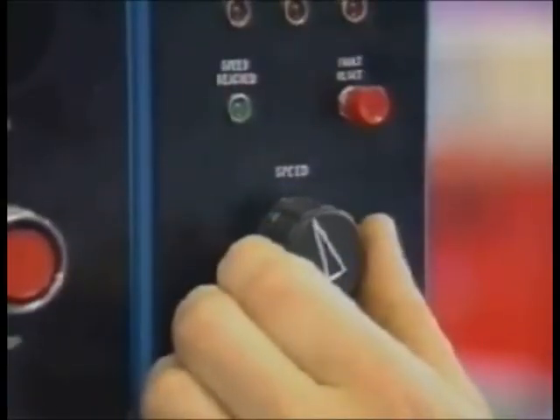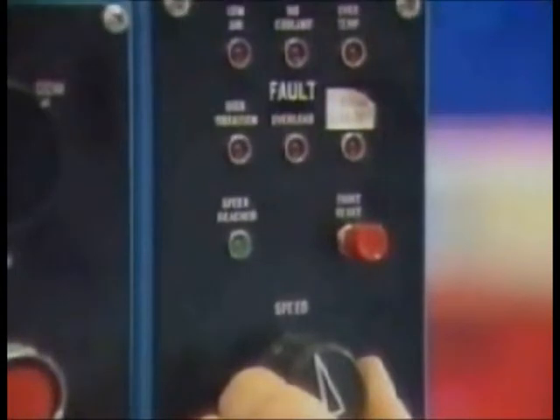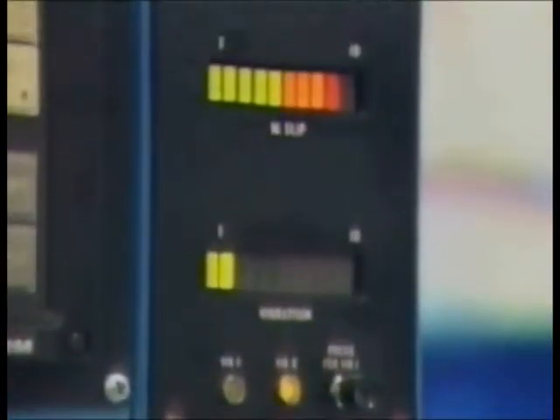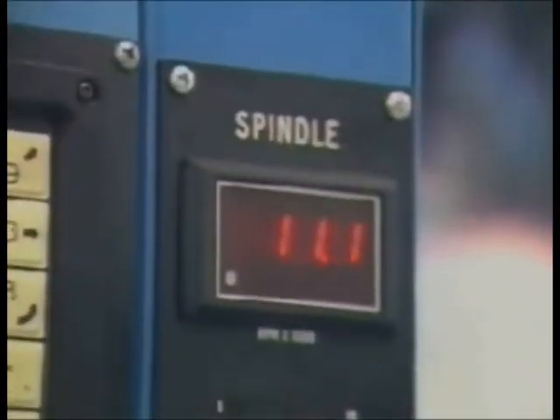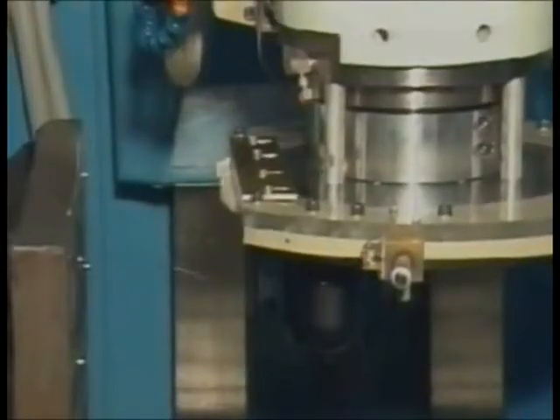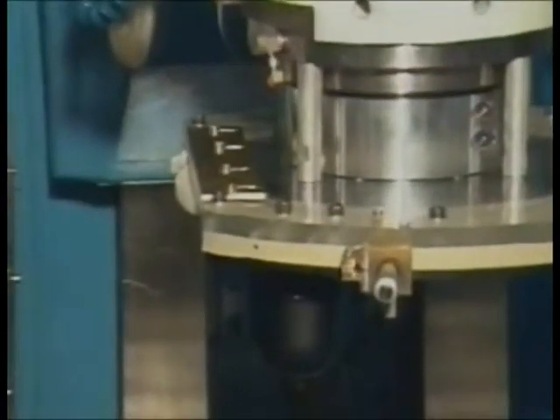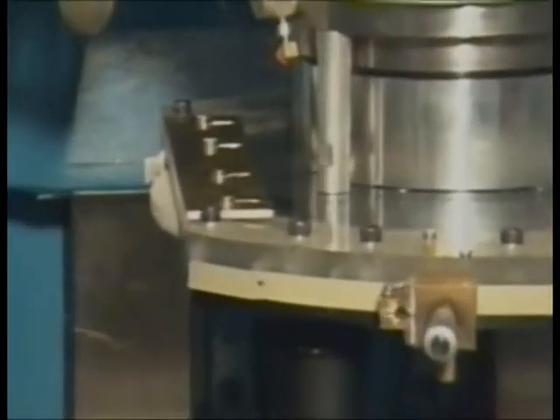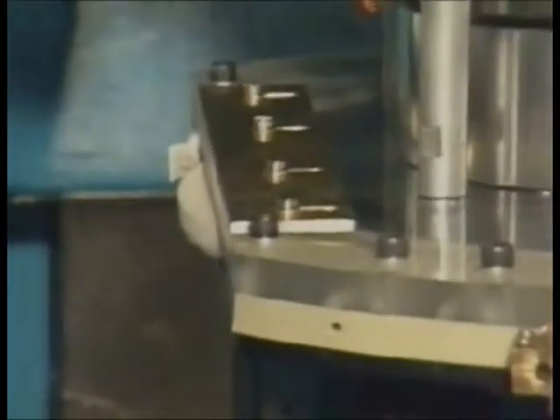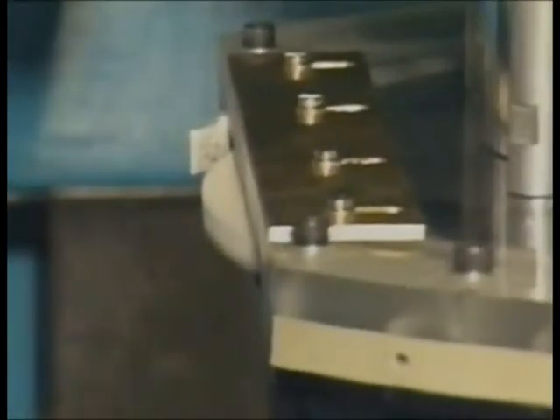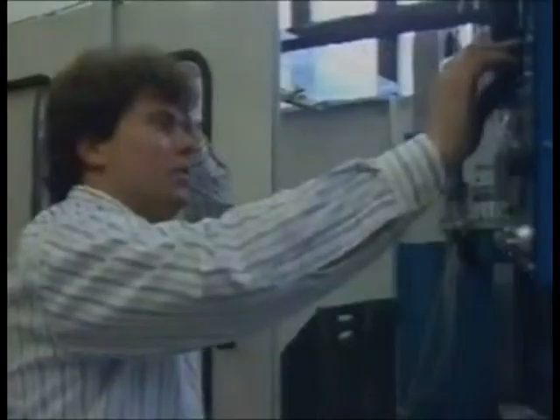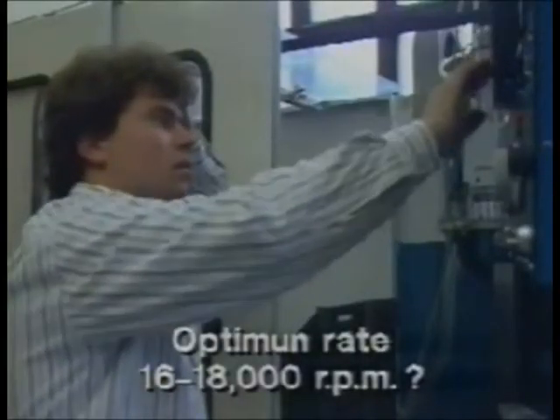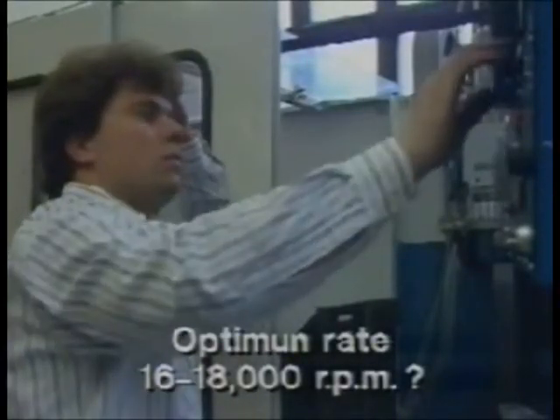The spin rate of the mop is dictated by its diameter and by the ability of the substrate to traverse the mop. Rates of 9,000 to 22,000 RPM have been used in experiments, but for mops of 200 to 300 millimeters diameter, a spin rate of between 16,000 and 18,000 RPM seems optimum.